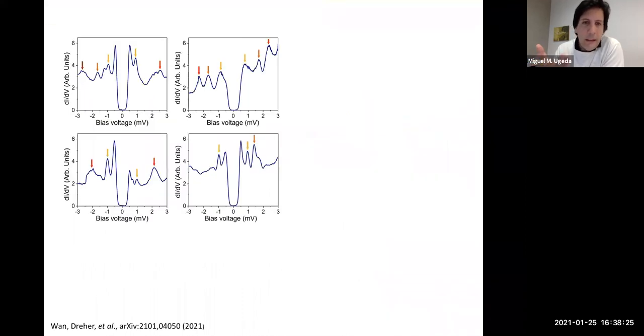Okay, so here I show you four different spectra, the dI/dV spectra taken in four different places with likely four different tip apexes, where you can see that the presence of these features is something quite common. And so, for example, if you look at this one, you have 1, 2, 3, 4, 5. Here you have actually 6 of them, and something that you can